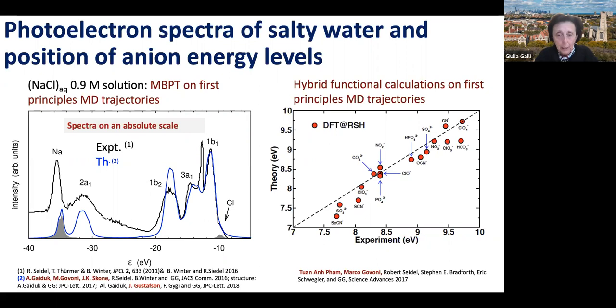Then we ask another question. And the question is, okay, suppose that there are a lot of other salts and a lot of other anions. Here they are listed here. And we could not do the simulation with all the GW simulation, spectroscopy, and so on and so forth. And we did the density functional theory calculation with range-separated hybrid. And you see the level, the top of the valence band, the one that determines the redox of water, the comparison between theory and experiment is not too bad. Actually, it's quite good. In some cases, you can live with the errors that are of the order of 0.3, 0.5 eV.